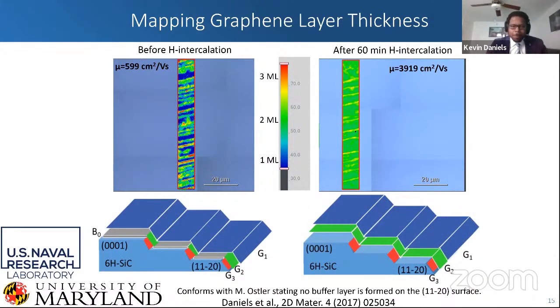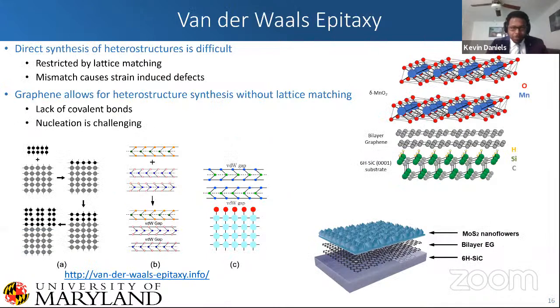Okay. So with all that said, now we can look at growing materials on top of this really great substrate. Direct synthesis of heterostructures is difficult because you have to lattice match. If you don't lattice match, you'll get strain-induced defects as shown below in figure A here. Now, graphene is great because for the most part, it lacks a lot of dangling bonds and covalent bonds. As a result, you can grow materials on top of it that won't bind to the graphene. This is called van der Waals epitaxy.